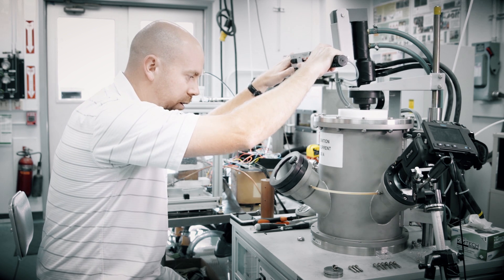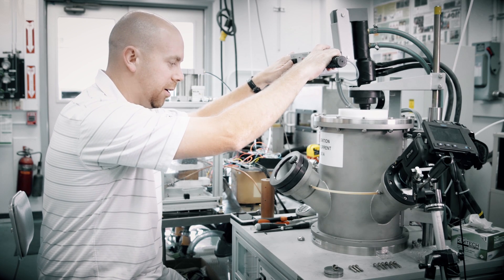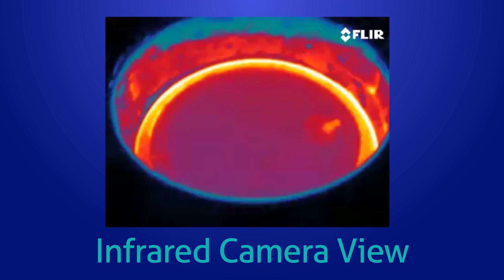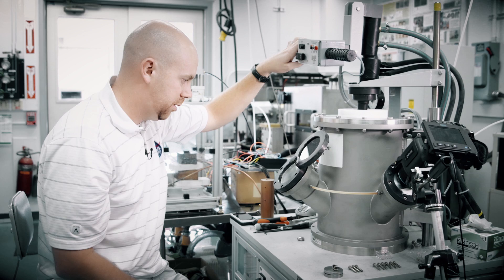Once I'm finished melting with the titanium getter and I've gettered the environment, I'll start melting a metallic glass sample in this well. I turn the arc on and move it around to try to homogenize the melt until it begins to flow, and once it begins to flow it will melt and mix itself. When I turn off the arc, you see the liquid moving around — that liquid is going to start to cool rapidly because it's touching a water-cooled copper hearth. At about 100 degrees a second, that liquid will cool and, because of the way the liquid is designed, it should cool into a glass — it should not crystallize. Here I'm turning off the arc and we're watching the ingot slowly solidify and cool. We see no crystallization events, which means the ingot has frozen into a bulk metallic glass.